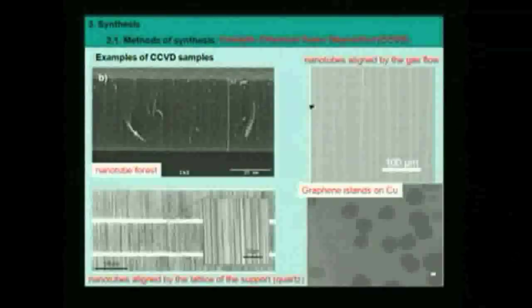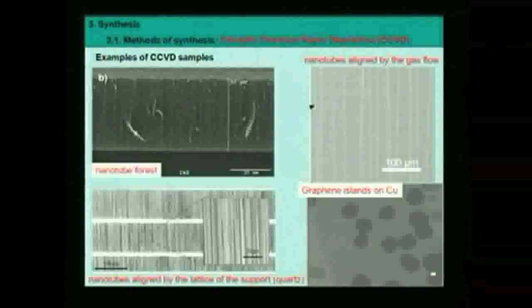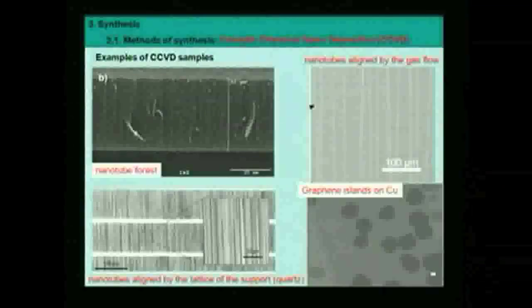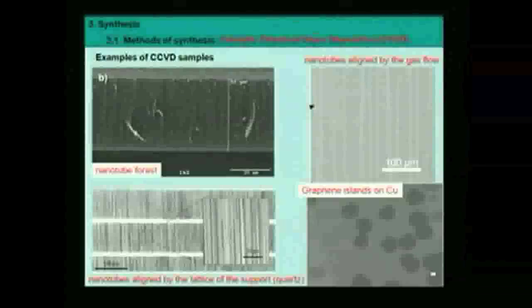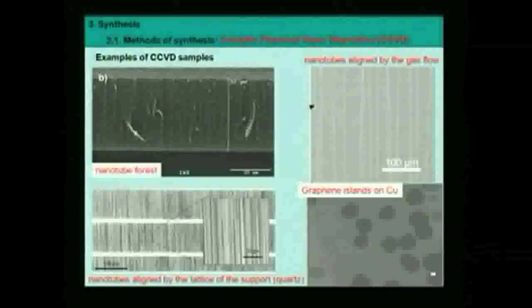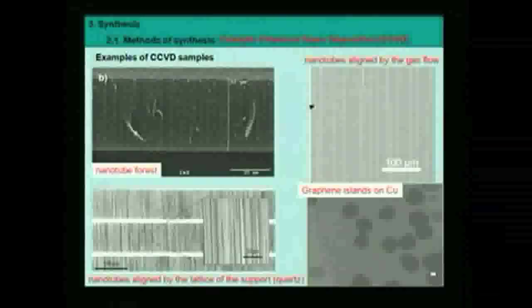Okay, another example here is the growth of graphene on copper. You see different patches here. Those patches are graphene deposited on a copper layer, a thick layer of copper. And the size of those graphene islands is a few tens of microns.